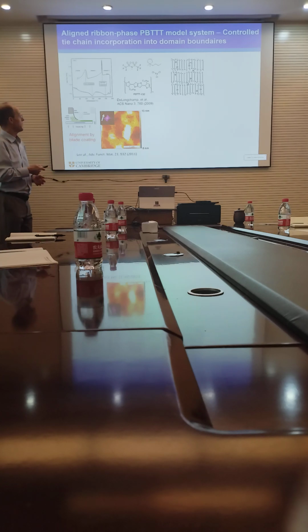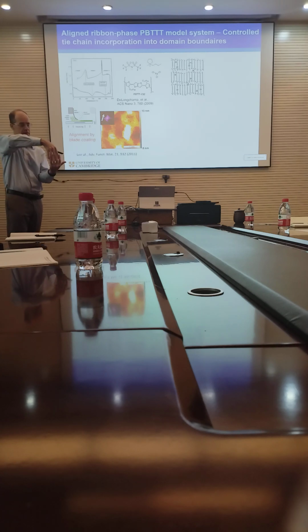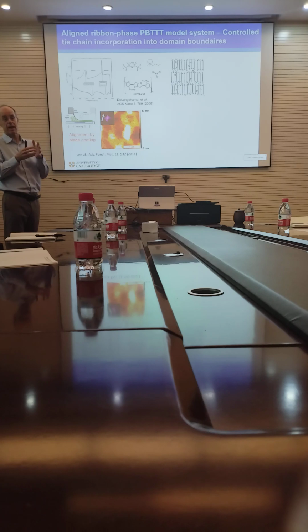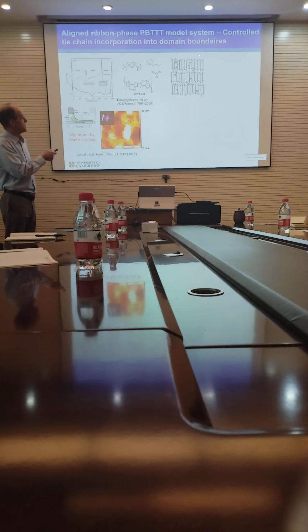So when you then cool down from that high temperature to room temperature, you have a structure where the polymer chains, in addition to having this lamellar microstructure, they also segregate into layers. So this is looking at the film top down. So you can see these individual polymer chains, these individual crystals nicely segregated. And then the chain ends are basically located in these grain boundary regions that occur on a regular periodicity. So this distance here would be the full chain, the extended chain length. Then you have a grain boundary, and then you have another polymer crystal here. And this is what we call the ribbon phase.